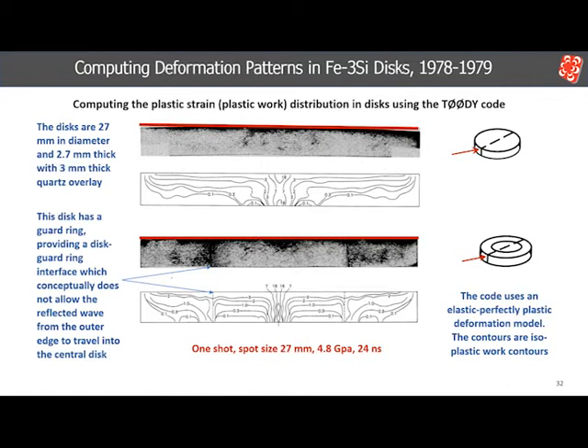The lower disc has a guard ring press-fitted onto a disc, with the intention to produce a much different stress wave interaction. With the guard ring, the tensile waves reflected from the outer rim of the disc cannot pass back through the interface into the central disc.